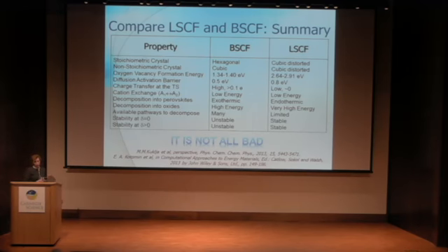and calculations of defects, stoichiometric crystals in BSCF are hexagonal, LSCF is distorted cubic. Recently we actually found that it's more orthorhombic, and distorted cubic and orthorhombic phases behave almost similarly, so it's difficult to distinguish between them. They probably coexist. Non-stoichiometric crystal, which has a lot of oxygen vacancies, is cubic in BSCF, and it's still distorted